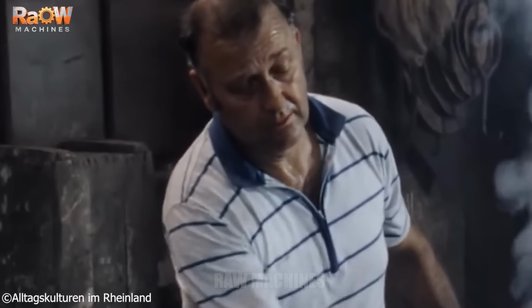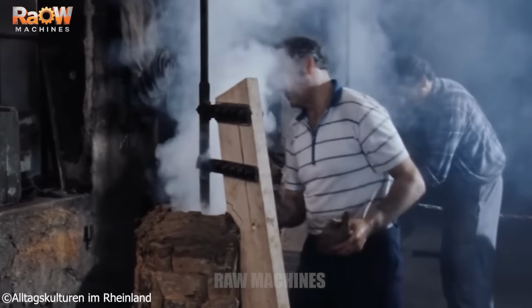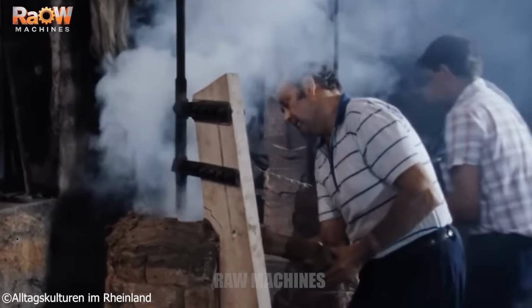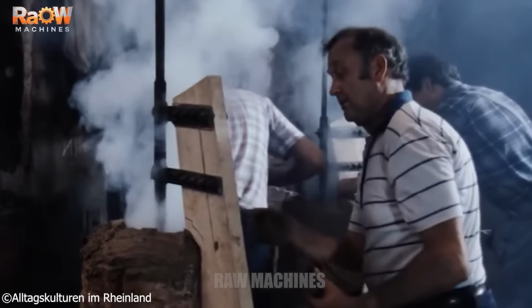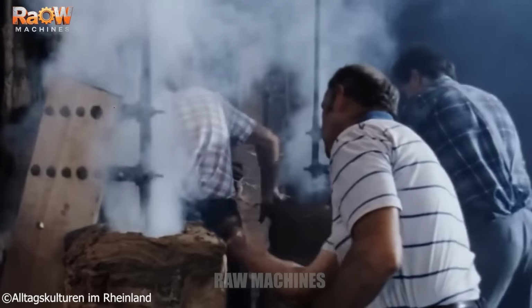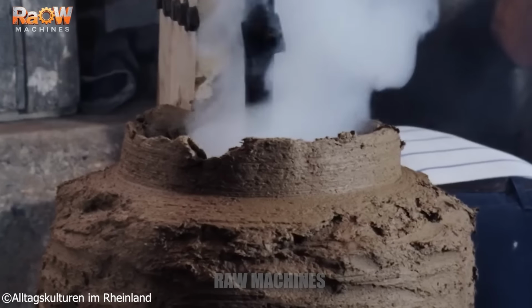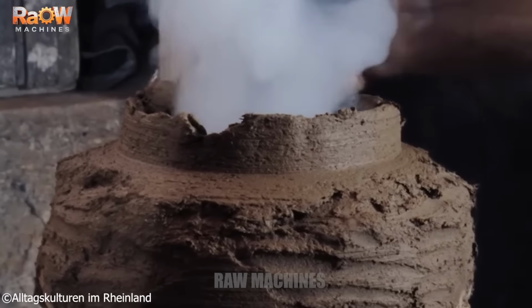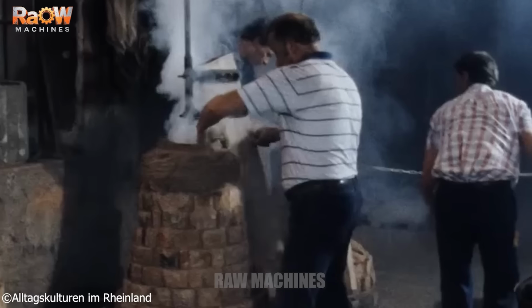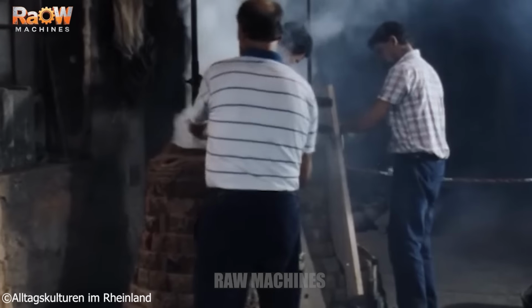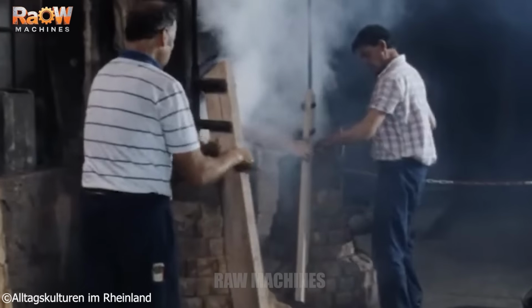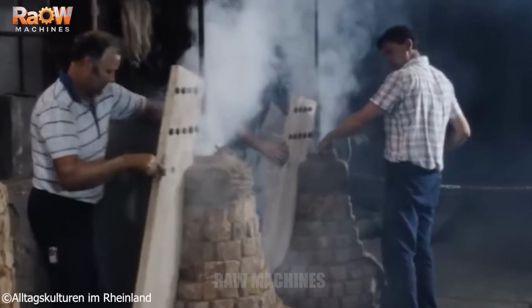At this stage, mold maker Hans Hein shapes the bell neck using stiff clay, followed by finer clay layers reinforced with jute fibers to increase cohesion and reduce cracking during drying. The entire core is fired overnight. Bell founders often liken the core to a tall brick kiln. Ventilation openings at the base draw in air, while the bell neck functions as a chimney.